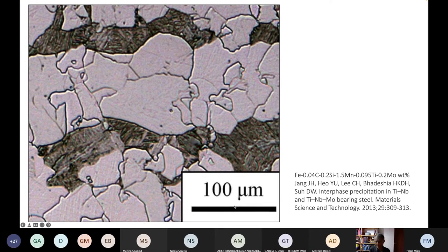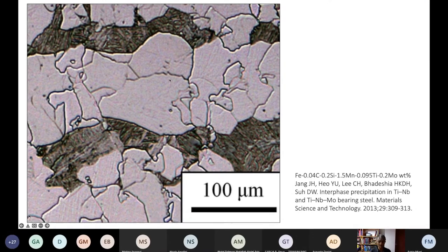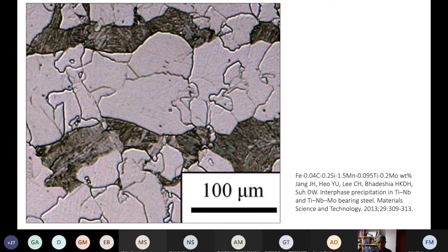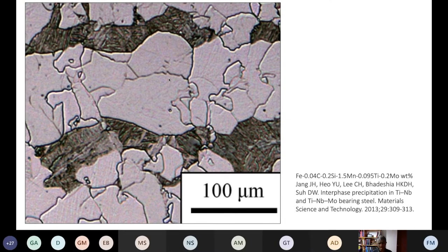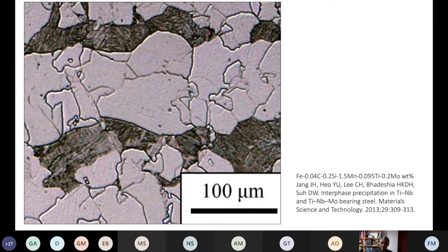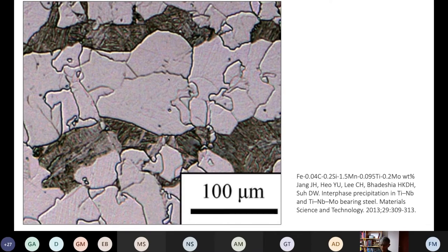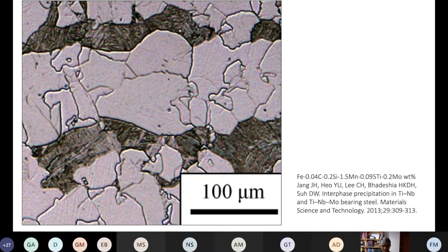This particular structure is quite coarse here — not the level of coarseness you would have in a properly produced beam. We know from a lot of work that if we can make the grain size smaller, then we get an improvement in both the strength and the toughness. So how do we make the grain size small?